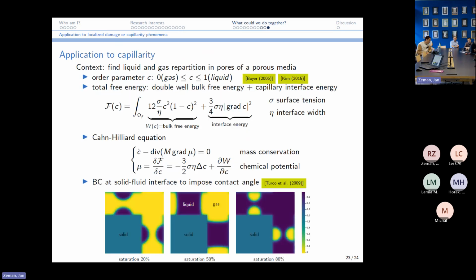And finally, something I really like to do from a personal point of view is to be able, when I have a 3D picture of the porous medium, usually in real life, in a concrete, you would have, say, gas and liquid within the pores, not only liquid or not only gas. Okay, so where is the interface between the two? And that has a huge influence on the mechanical response and all the transport properties. So I would like to be able to see where is this liquid-gas interface.